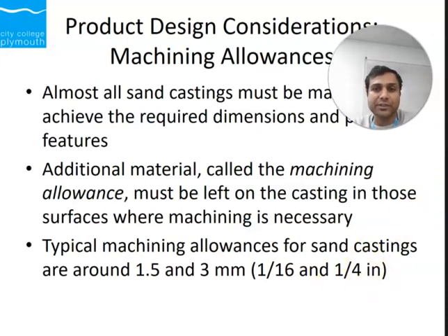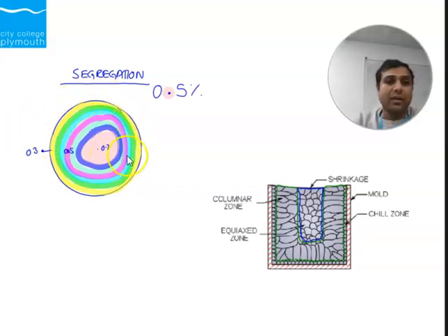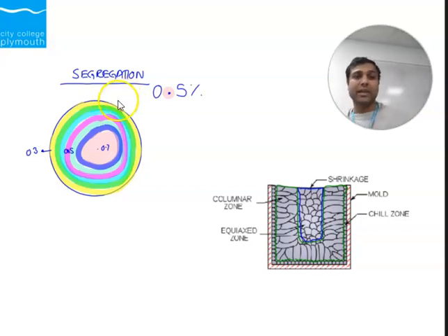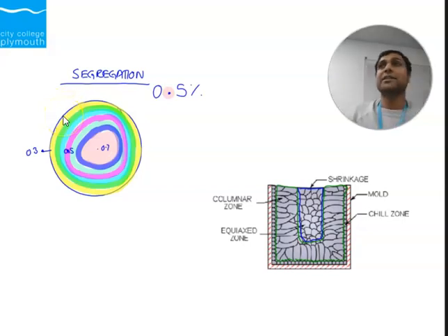Now, if I show you the microstructure and what I meant by segregation, imagine we are doing the casting, and that's the sand casting. The die is on the outer side. When the material starts to solidify, it will start to solidify next to the boundary. And imagine this is steel. So what will actually happen is the first layer that solidifies, steel, which is iron and carbon, has a lower percentage of carbon. And the material that solidifies next has more percentage of carbon. And as you move inside, because the yellow is the one that will